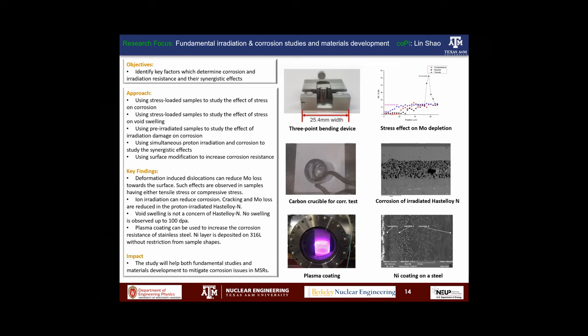So a few nuggets on this task. One of the tasks is to study the effect of stress on corrosion of alloy N. And this is achieved by using a 3-point bending of alloy N and corrosion comparison of the different regions under various stresses. Another item is to study the effect of irradiation on the corrosion of alloy N using proton irradiation to induce dislocation in the network.